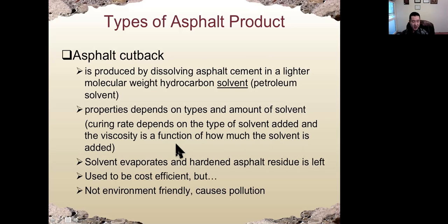The second one is asphalt cutback. Asphalt cutback is produced by dissolving asphalt cement in a lighter molecular weight hydrocarbon solvent. The hydrocarbon solvent is also coming from crude oil. So the property depends on the type and amount of the solvent. The curing rate, which is how soon the asphalt cement hardens, depends on the type of solvent we use, and viscosity is a function of how much solvent we add, since we need the solvent to liquefy the asphalt cement.